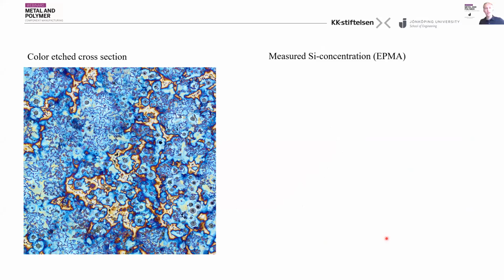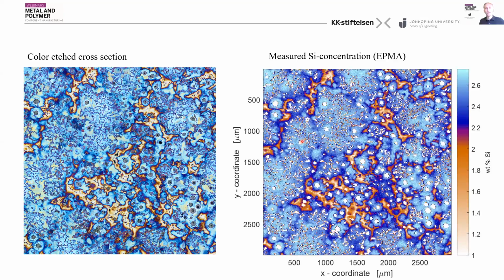So on the left here, you have a color etched surface of compacted graphite iron. The blue regions here correspond to the regions which are rich in silicon, and the yellow regions have lower concentrations of silicon. And we measured the same region with EPMA to map the concentration of silicon in this region. On the right, you see the map of the silicon concentration. Here we have used a color scale on the concentrations which imitates the effect of the color etching in order to make a closer visual comparison. And you can see that it correlates very well with the patterns you see after color etching.